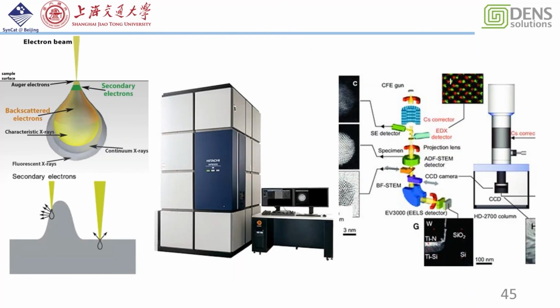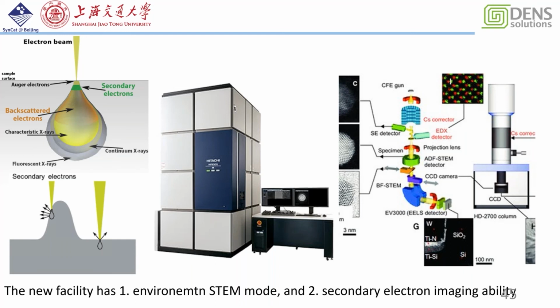But here we use another very different technique. This is embedded in the Hitachi TEM called HF5000. They put the secondary electron detector inside this e-STEM. So firstly, with this technique we can introduce the gas inside to do the environmental TEM work. But also they have a secondary electron detector, so they can get the very surface information, which helps us to understand the topography of the catalyst and about the surface.